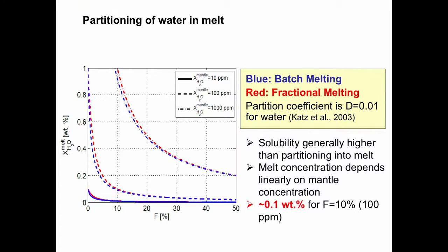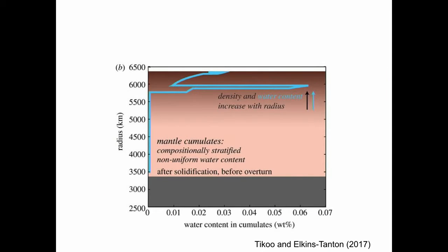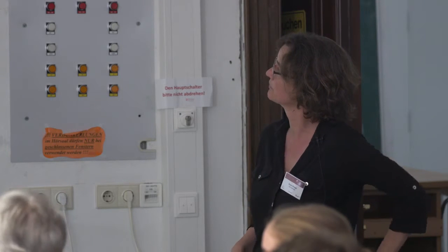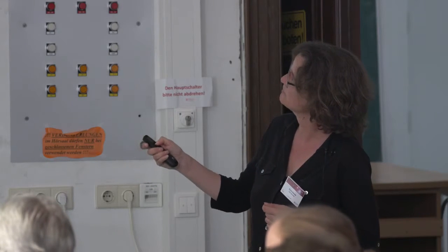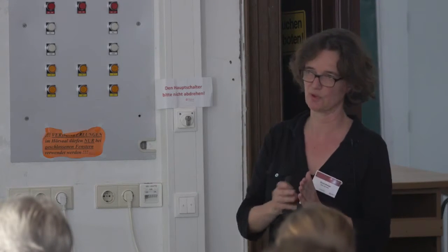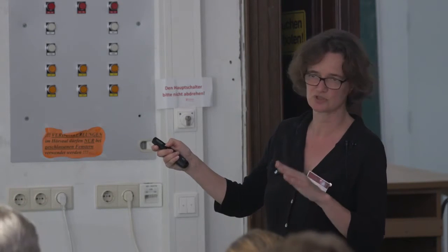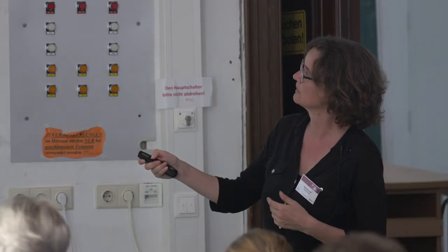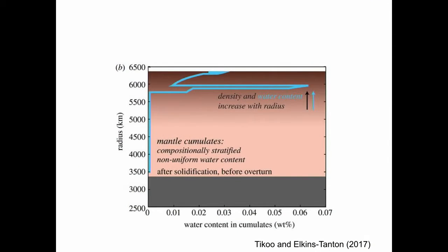So you start crystallizing. A little bit of water goes into the crystals, and what you see here is the profile of the volatiles in the solid material. The closer you get to the surface, the more strongly the melt is enriched in volatiles. So in other words, that means the rocks you form later also contain more volatiles. Because there is a partition coefficient between the silicate and the liquid. And whether you have a peak here depends on the minerals you crystallize. They have different partition coefficients. For the lower material here, the partition coefficient is very small. Then there's an increase, probably garnet which is crystallizing here, which can take up more water. Then you again have a decrease, and here you have an increase of water in the solid part.